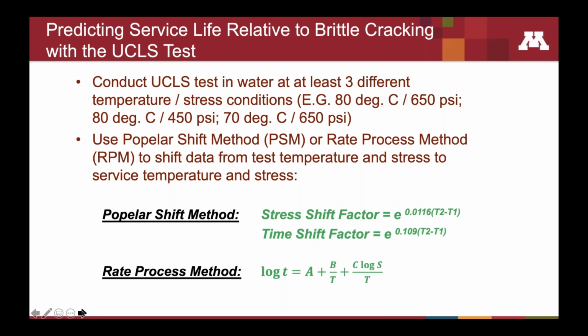And the reason we do that at 3 different conditions is you'll notice the equation, particularly the lower one, the rate process method, has 3 constants in it, A, B, and C. So the way we want to solve for those constants is to at least have 3 different equations. If we have 3 equations, we can solve for those 3 unknowns and determine the log T, which is the log of time to failure, as a function of stress and temperature.